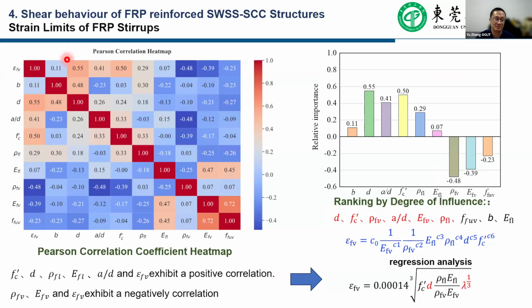Therefore, we also develop a Pearson analysis for this method. We can find that the concrete strength, the effective depth, the longitudinal reinforcement percentage, the elastic modulus of the longitudinal FRP bars, and the shear span ratio have a positive correlation with effective strain. And furthermore, the ratio of the FRP stirrup and the material elastic modulus of the FRP stirrup exhibited a negative correlation. We use that to develop a statistical analysis. After some regression analysis, we establish a function to predict the effective strain for the FRP stirrups.